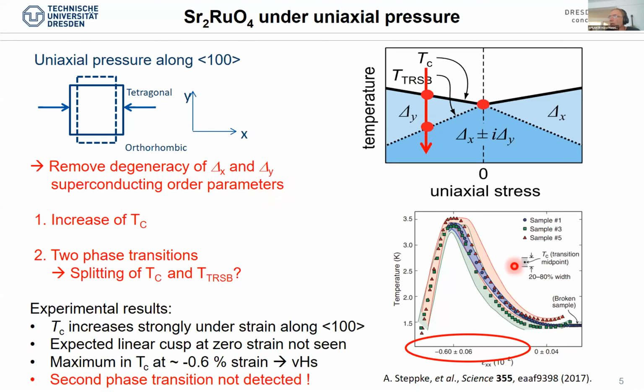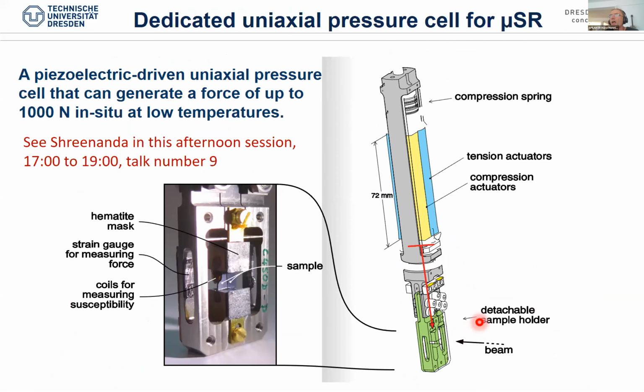Yeah, and you already saw that the Tc strongly increases in the experiment. Really, there is here, close to the Van Hove singularity, a strong maximum. And we want to see what we can see with muons under uniaxial strain if we go through this kind of strain system, uniaxial strain. However, we could not use the small cells which you can commercially buy.